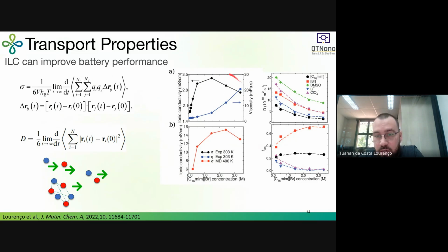this decrease here is because when we look at the displacement of the ions, at the diffusion coefficients of these ions, we see that they are always decreasing. So that means that we are increasing the concentration of ionic liquid, with more charge carriers, but they are getting slower and slower. And after this point, they are too slow, so even if we add more ions, there's no increase in the ionic conductivity. So we understood what's happening here.